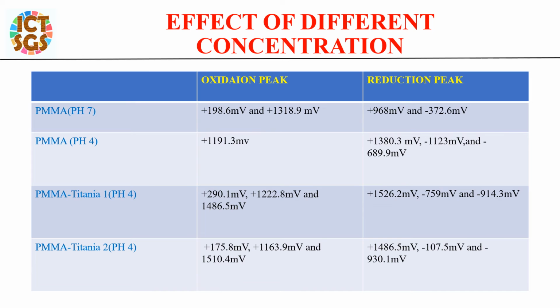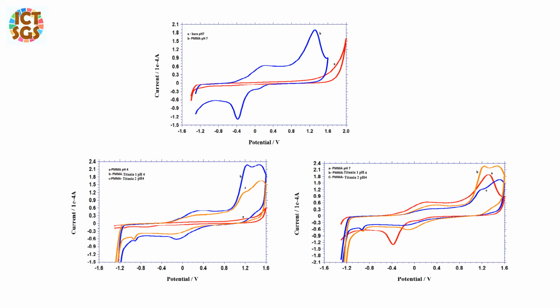Here, the low concentration of titanium PMMA nanocomposite enhances the conductivity at pH 7. The peak current also increases, confirming the presence of titanium nanoparticle in the polymer matrix by electrochemical study. At the same time, the conductivity is low at high concentration of titanium PMMA nanocomposite due to the increase in the concentration of titanium in PMMA. All these results clearly indicate significant enhancement in the ORR electrocatalytic activity for the nanocomposite PMMA titania compared to PMMA. This is a cyclic voltammetric response obtained for PMMA and PMMA titania 1 and 2 modified glassy carbon electrode with a scan rate of 100 mV per second at pH 4 and 7.